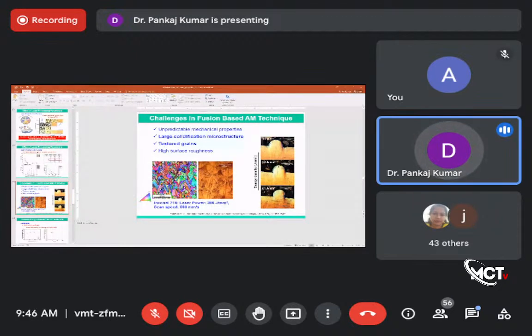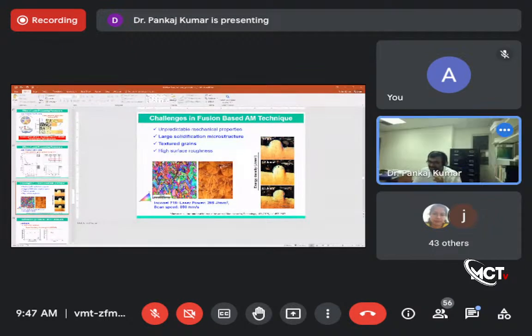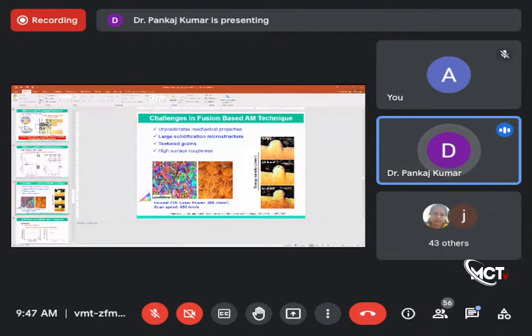So microstructure actually changes the properties drastically, right? You want a very spherical kind of microstructure, spherical grains. But in the additive manufacturing process, you have elongated grains, and because of the elongated grains, you have texture in the material, right? Your properties are directionally dependent. So it's very hard to keep track of the directions. When you use any material, you don't really think about the directions before using it. You just simply use it.